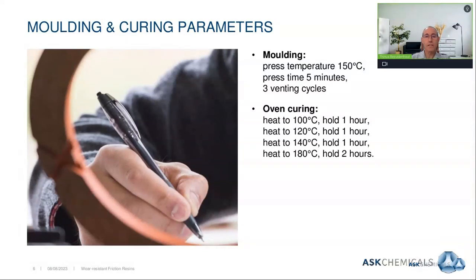For the oven post-curing, we have chosen a program whereby we heat to 100 degrees Celsius and hold it for 1 hour to give time for the moisture to escape. We then heat to 120 degrees Celsius, hold it for 1 hour again to make sure that the ammonia gases from dissociation of hexamine have escaped. It is then further heated to 140 degrees Celsius to facilitate the cure further, and finally to a top temperature of 180 degrees Celsius for the final post-curing, where we hold it for 2 hours.